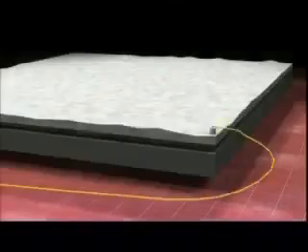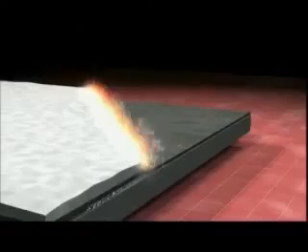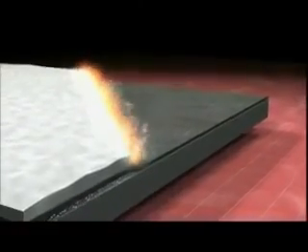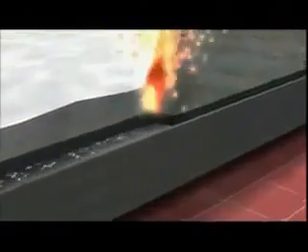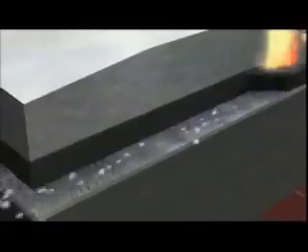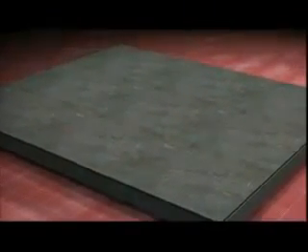The explosion is detonated from one edge of the cladder and moves across the upper level of the pack at a uniform speed. This explosive front progressively drives the cladder plate downward toward the backer at the slight collision angle caused by the standoff gap. Forward of the collision point, air is forced out of the gap at high velocity. All oxides and impurities are expelled, rendering the plate surfaces metallurgically pure and ideal for a weld. As the backer and cladder collide, the weld is created nearly instantaneously across the entire surface of the plate.